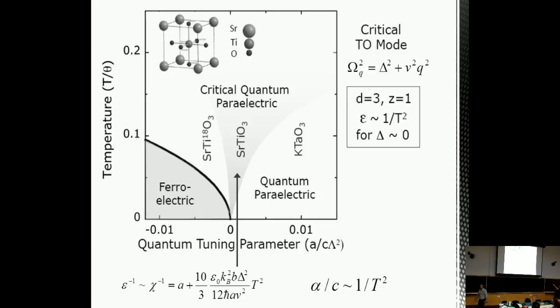So there's the normal phase here of the quantum paraelectric, which would be the analog in the insulating state. Instead of, say, a T-linear resistivity or a logarithmic heat capacity, here we have a quadratic electrical susceptibility. This phase is a very interesting phase itself. And if you dope it, there is something very interesting in strontium titanate. It has a quadratic resistivity over a very wide range of temperatures. But this is not a Fermi liquid quadratic, because the Fermi energy can be less than 1 Kelvin. So you're measuring quadratic resistivity in an area where you don't really have a Fermi surface. And the normal state behavior is currently not explained.